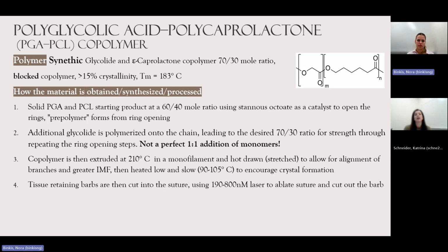It's a synthetic glycolide and epsilon-caprolactone copolymer with a 70-30 mol ratio. It's a block copolymer with about 15% crystallinity and a melting temperature of 183 degrees Celsius. So you start with solid PGA and PCL at a 60-40 mol ratio, using stannous octoate as a catalyst to open the rings. A pre-polymer forms with ring opening. Additional glycolide is polymerized into the chain, leading to the desired 70-30 ratio for strength throughout repeated ring opening steps. This is not a perfect one-to-one addition of monomers.